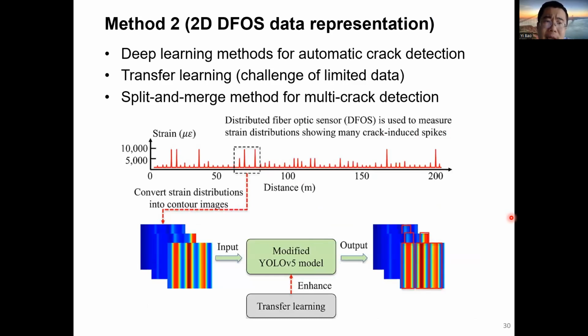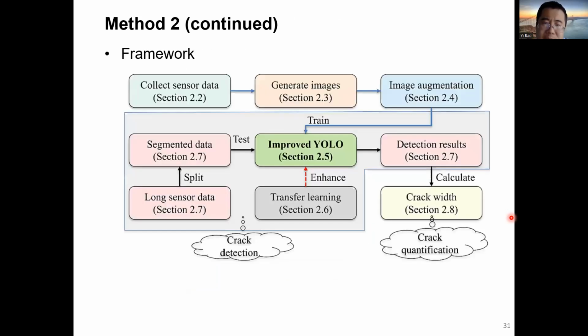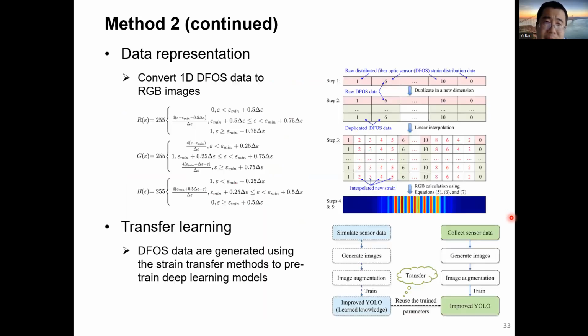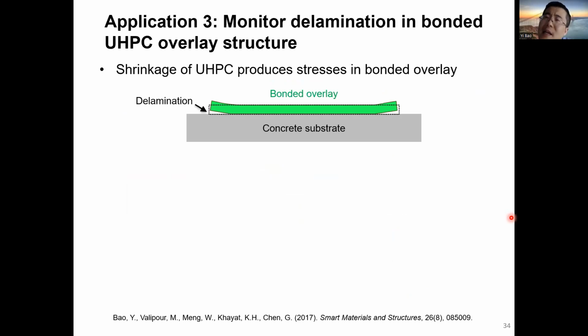The second method is to utilize the deep learning technologies. Well, when we do the measurements from the distributed sensor, we measure the strain versus distance. So this kind of curve was converted to an RGB image. This kind of RGB image was then analyzed using some deep learning technologies. And we also applied transfer learning to improve the accuracy. So eventually we were able to use machine learning methods to automatically analyze the distributed sensor data for monitoring cracks.